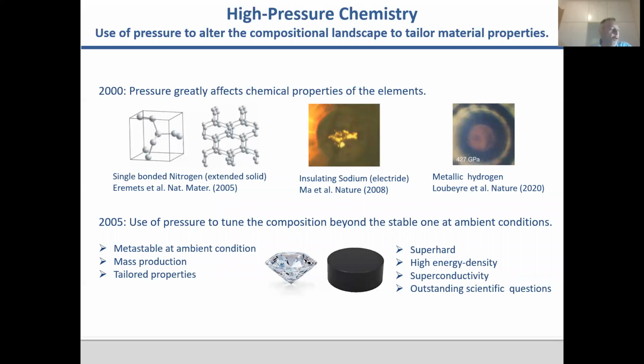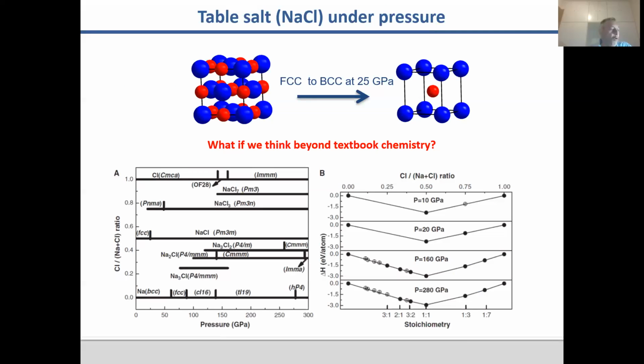So just to start, I will give you an old example of what exactly we mean by new stoichiometries. This is a relatively old paper now, from Science 2013. We deal with a very simple system, rock salt, sodium chloride. If you just take sodium chloride and apply pressure, you will see a phase transition at about 25 GPa, which nowadays is kind of trivial. Now the idea is, can we think beyond textbook chemistry? Can we think about stoichiometries beyond what the periodic table says, the one-to-one? And it looks like, at least from the theoretical point of view, even at very low pressures, 20 GPa, stoichiometries which are rich in sodium or chlorine become stable.